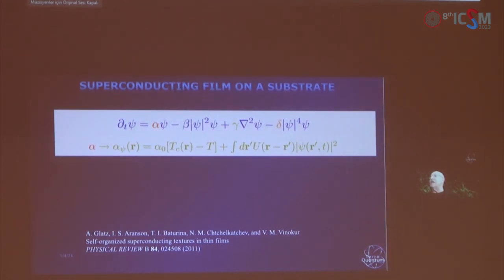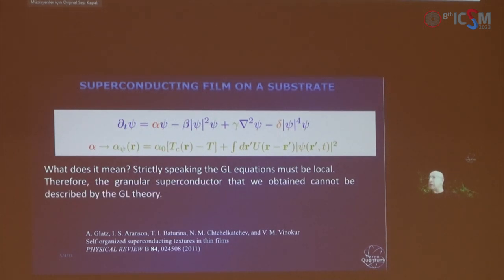So the basic change was in this fundamental parameter in the Ginzburg-Landau equation, which converted the Ginzburg-Landau equation into a non-local one, because different points are connected to each other by this long-range elastic interaction. Strictly speaking, this means that the Ginzburg-Landau equation, which must be local, does not apply to this granular superconductivity, and the granular superconductivity which we observe in numerical simulations cannot be obtained and described by Ginzburg-Landau theory.